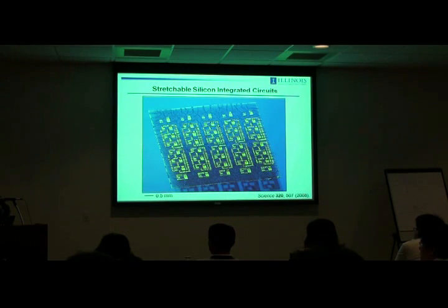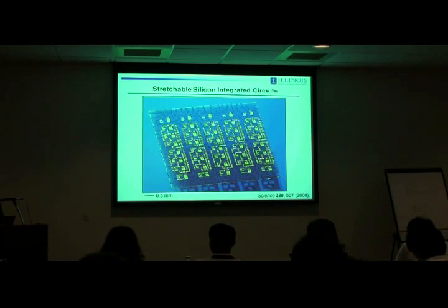So there depends on the thickness of the substrate. There is some residual stress in the system. So the top surface is a little more highly stressed than the bottom surface because it's mechanically loaded by the circuit. If the thickness of the bottom substrate is sufficiently large, then you can get an overall bowing effect rather than local wavy shapes. I'll show you in a couple of slides a more advanced design that we more routinely use these days that avoids that kind of problem. It was a very good point.